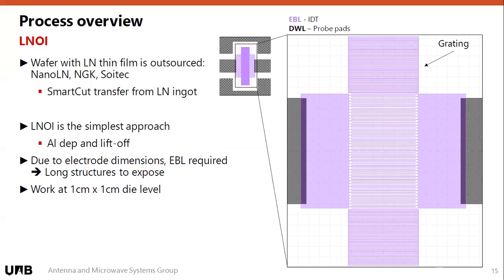And this is the structure we're going to be defining. So you have a grating on the top, then you have the central body of the reflector with another grating, and then the busbars. Since we have a 500 nanometer, more or less, electrode width, we're going to be resorting to electron beam lithography, because this could also be done with a stepper, but we went for the electron beam lithography. And it also provides you a higher degree of flexibility because you can play with your design, rerun and change things. The only problem we might run into, that Albert and Chevy solved, is that you have long structures here, really long fingers, really tight spaces.